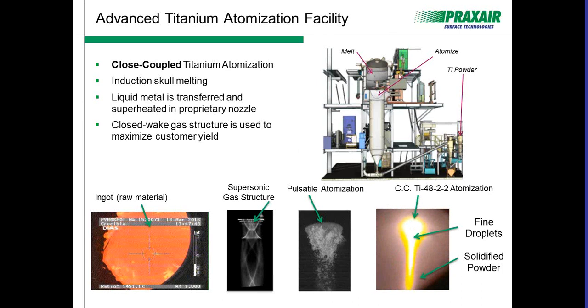This is a cross section of our titanium atomizer, in which you see where it melts here. It's driven down the large tower. We use high purity argon to drive the solidified particles to a collection vessel, in which we then collect the titanium after the run on each batch.